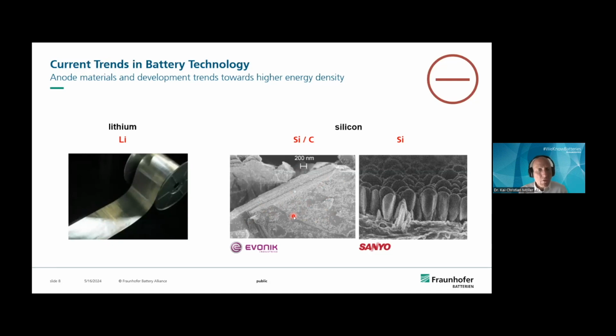Silicon can store large amounts of lithium, but the volume expansion is approximately 300%. And this has to be handled in the electrode. It's also possible to use pure silicon, but the technology is a little bit different. It's a vacuum deposition of silicon on a structured copper foil, and these columns, let's say, breathe and make the battery electrode thicker and thinner during uptake and release of the lithium ions.